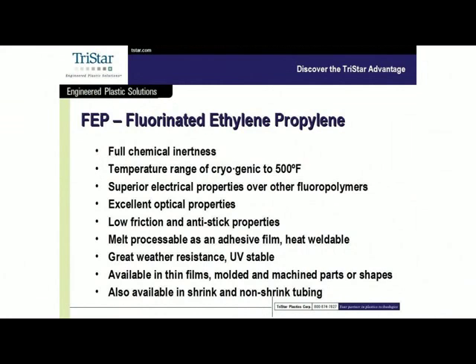FEP has very low friction, not as good as PTFE, but of all the other melt processable fluoropolymers, FEP is one of the better ones in terms of its inherent low friction properties. And anti-stick. FEP is very common as an anti-stick coating. Most of these melt processable resins can be used as coatings, so they all have a very specific place that they can be used to coat metal, to coat other plastics. So the FEP has one of the better coating values in terms of its non-stick properties.